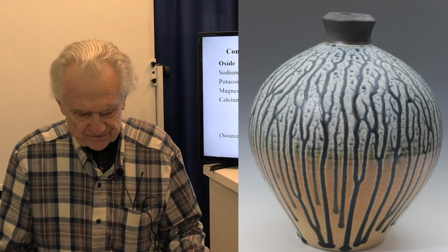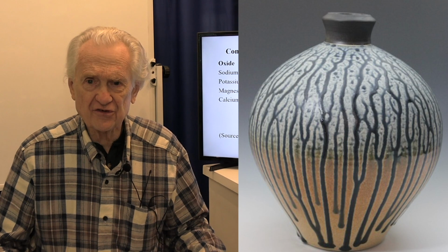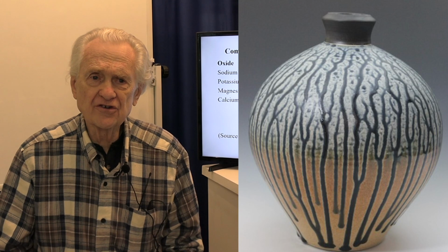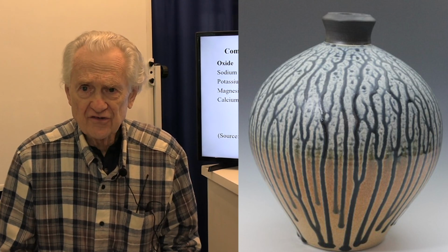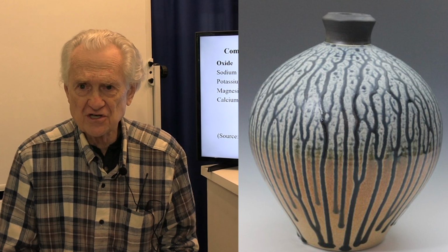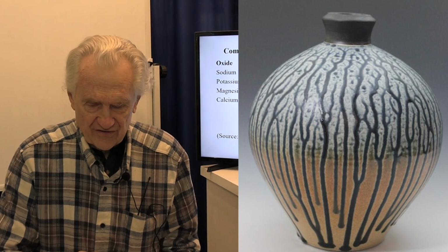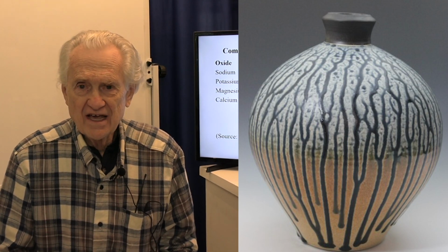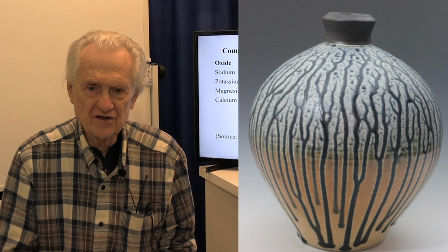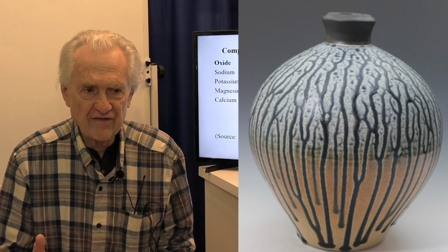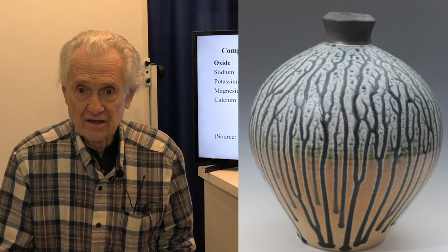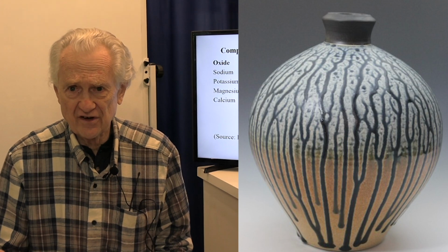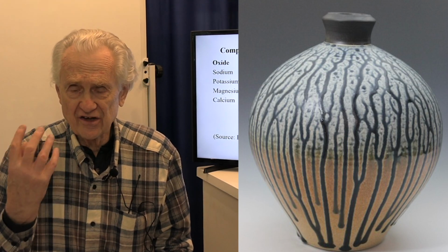For washed ash, I recommend the same pre-screening to remove the coarse chunks of charcoal and maybe any nails or metal hardware. And then you take the ash and soak it in water. What I've done before is take a plastic garbage can and just throw it in, and proportions don't matter. Just throw it in the water and stir it, and then let it sit overnight. And again, be careful, because now the water part of that mixture is actually lye. It's very caustic, and it can create burns on your hands, especially if you have sensitive skin, and you definitely don't want to get it in your eye because it will burn your eyes.